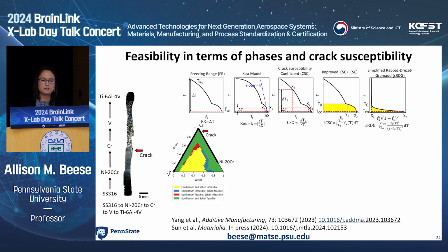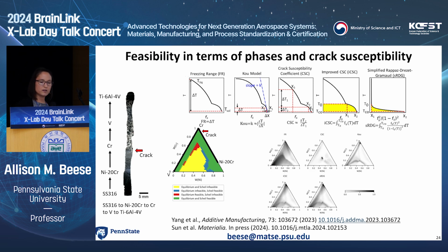So we also now have integrated welding solidification crack susceptibility criteria, where each of these 5 criteria are different methods to say whether or not you expect a crack during solidification. And each of these are in different scales, but if we normalize these and plot these, we can see that each of these has a hot spot where chrome is introduced. So that would be represented by a dark region in our crack susceptibility.